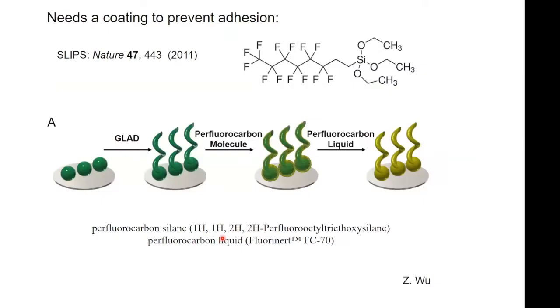And this coating is something which is very similar to medically approved fluorocarbon compounds. And it's very, very slippery. You know, fluorine-type materials from your Teflon frying pan. And so here now the task was to take these drills, to coat them with a perfluorocarbon silane, and then even to put on a perfluorocarbon liquid so they don't aggregate and move.